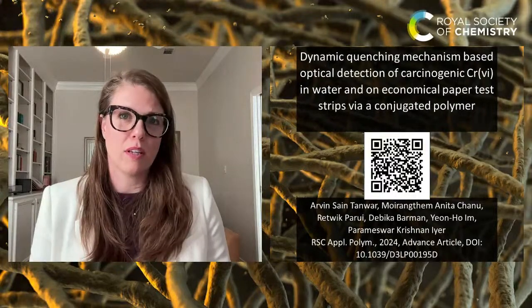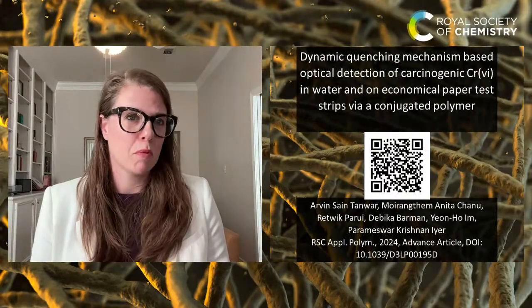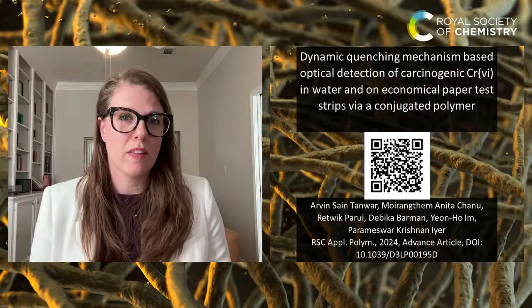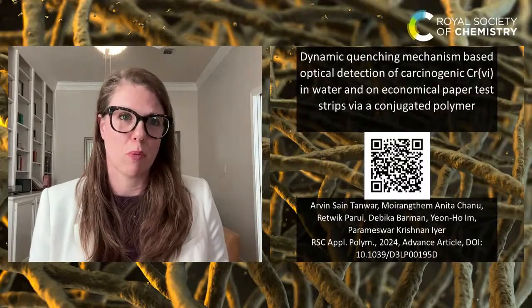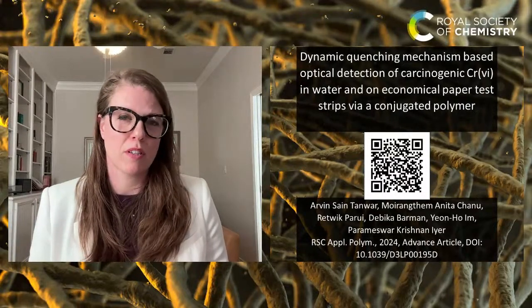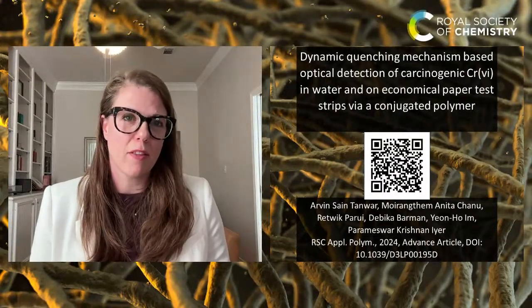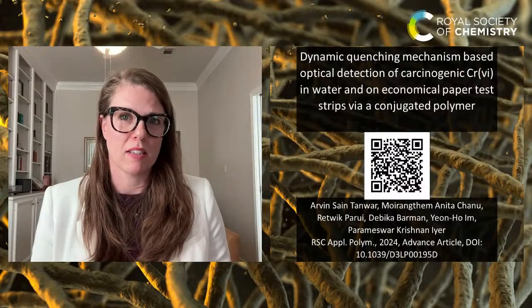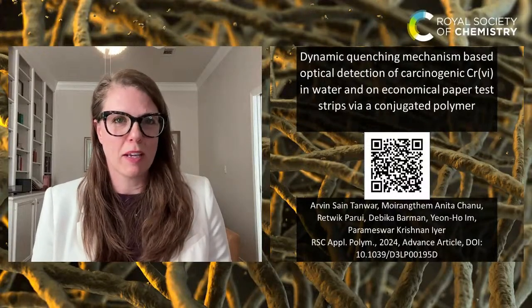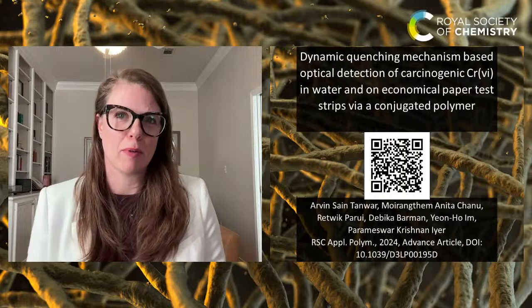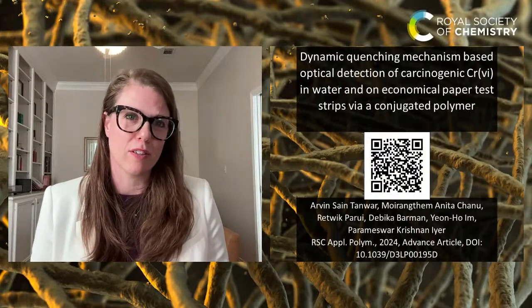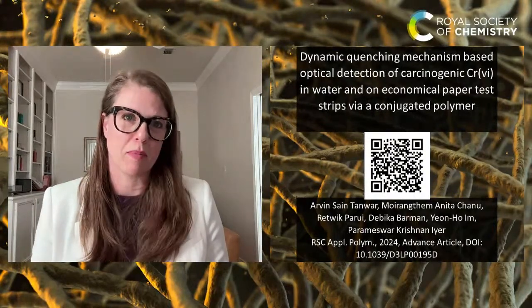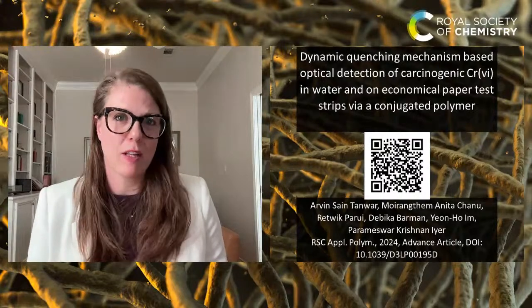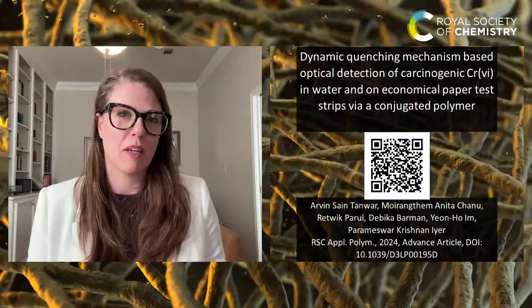The authors also deposited the polymer onto simple lab filter paper and showed that they could use this to visually detect chromium-6. By using a Stern-Volmer plot and evaluating time-resolved photoluminescence data, the authors established that a dynamic quenching mechanism is occurring. And I'll just make a note that this paper contains a very nice table comparing this polymer-based system to others for the optical detection of chromium-6. This paper is now available online and has been published and will be in the next issue.